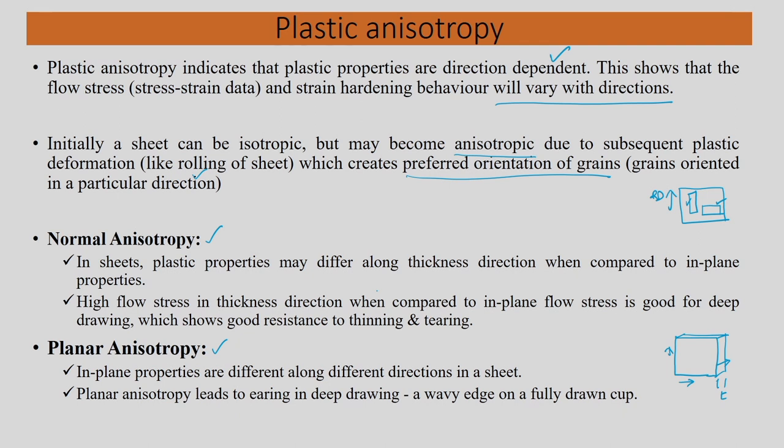So, you need to quantify it. For example, this is just an example: high flow stress in the thickness direction. Suppose you can measure the thickness direction flow stress, okay, how we will see later on briefly. High flow stress in the thickness direction when compared to in-plane flow stress is good for deep drawing. Suppose you measure flow stress along the thickness direction and along the in-plane direction, okay, and high flow stress in the thickness direction is preferable to have a good deep drawing.